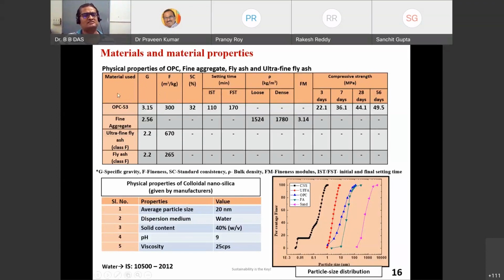And you can see here all the materials like OPC, fine aggregate, ultrafine fly ash. And these are the physical properties of the nano silica. Actually, we procured the nano silica from a lab in Mumbai, and they are the people who supplied continuously depending on our requirement. The particle size we restricted to 20 nanometer. The dispersion medium is water.